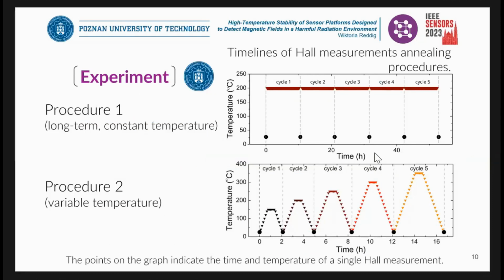So to see if the changes that we measured were caused by radiation or high temperature, we devised 2 procedures. One, pictured above, long-term with constant temperature, was mimicking the conditions that were present in a nuclear fusion reactor. The samples there experienced 50 hours of annealing at about 200 degrees Celsius. This picture is only a simplified version. We actually did 5 cycles lasting 10 hours each at 200 degrees Celsius.